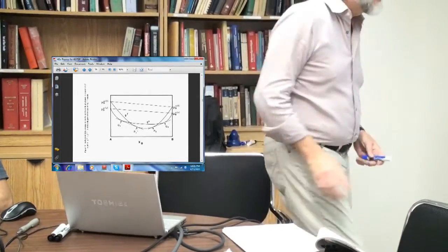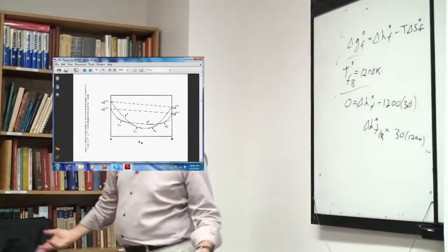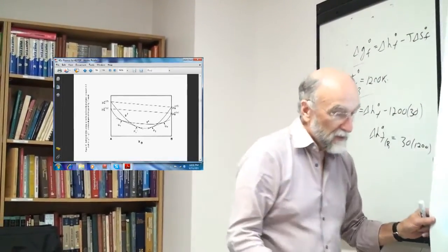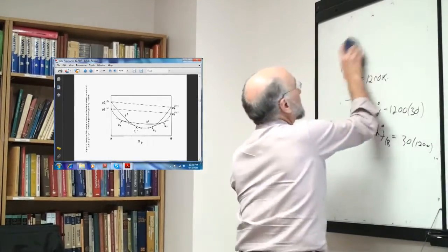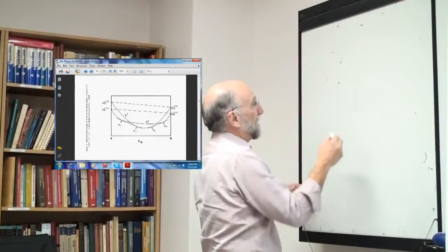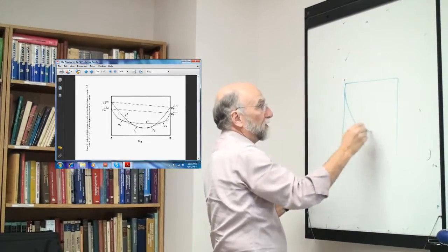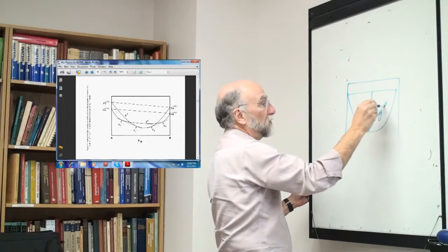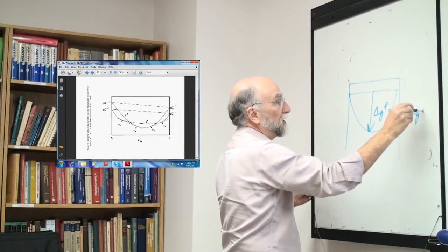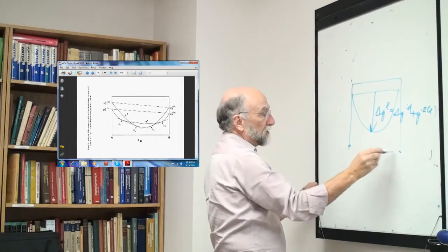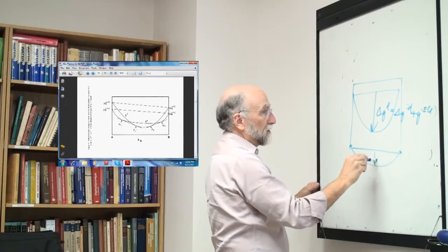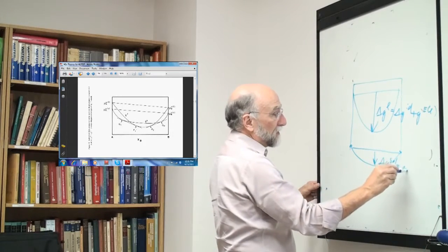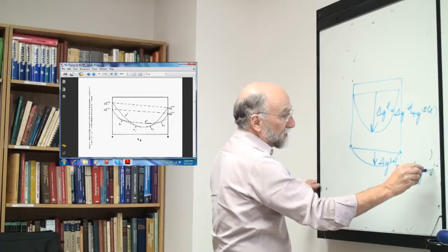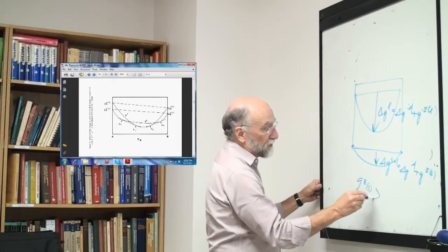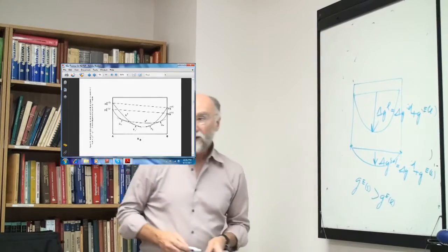This is due to the excess properties. Okay, so due to the excess properties, you simply have your liquid curve. This is delta G liquid, which is delta G ideal plus G excess of the liquid. And for the solid curve, you have a curve like this, where delta G of the solid equals delta G ideal plus G excess solid. So clearly G excess solid is greater than G excess liquid, more positive or less negative or whatever. Okay, but it's the relative.